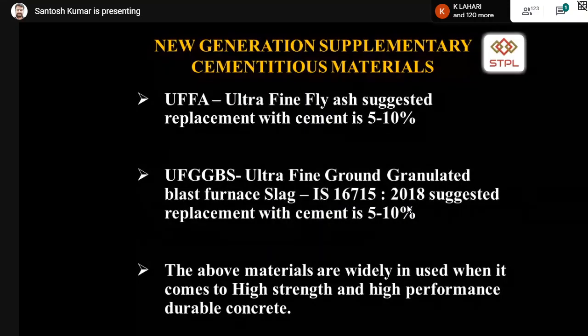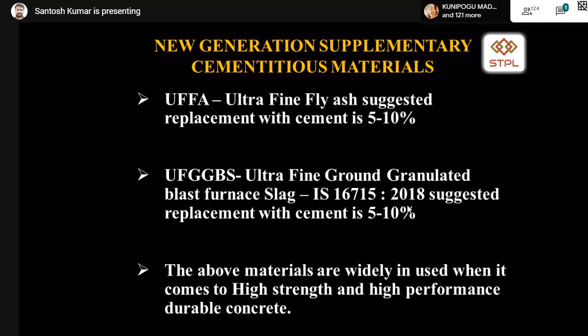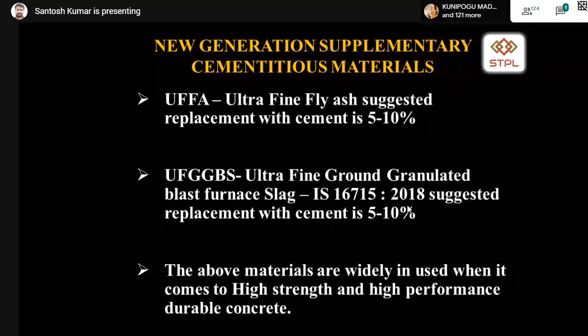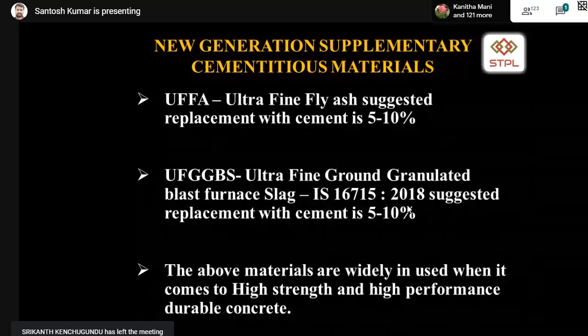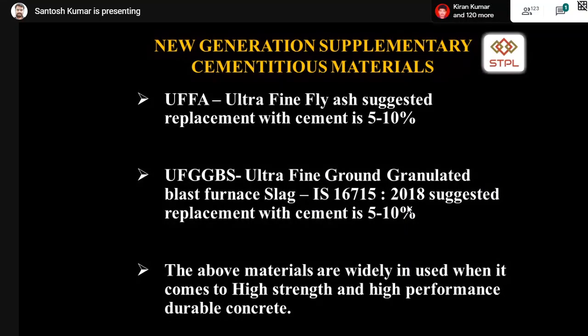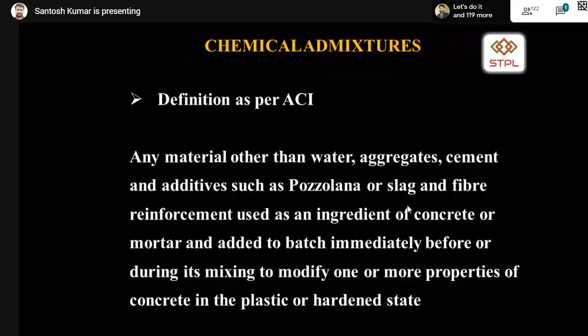And these materials are strictly to be used only when you are dealing with high strength concrete. Ordinary concrete, if you add this, it is a very huge loss. The mix is not economical because these have a very high cost. The cost per kg of cement is 7 rupees. Cement you get for 7 rupees, fly ash 1 or 1.5 rupees, GGBS 2.5 to 3 rupees, ultrafine fly ash 12 to 15 rupees, ultrafine GGBS 20 to 25, and micro silica will cost you 23 to 25 rupees per kg, I am telling. So these materials should be used only when you are using high strength concretes.